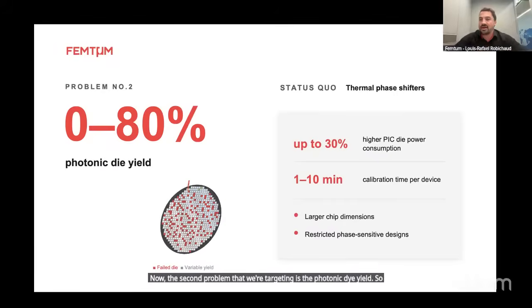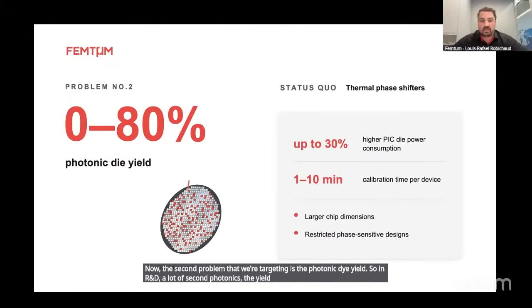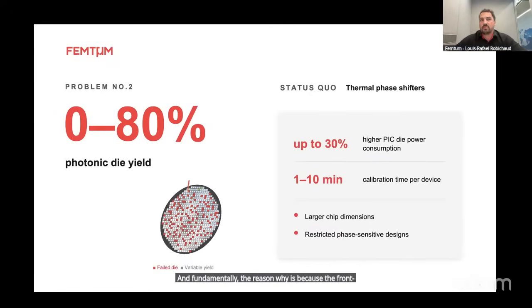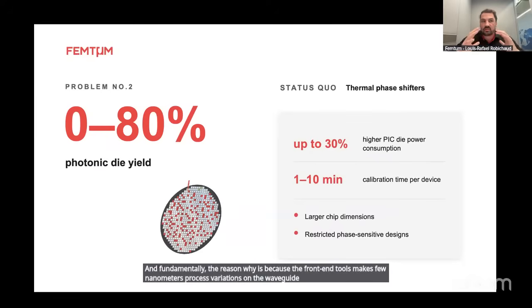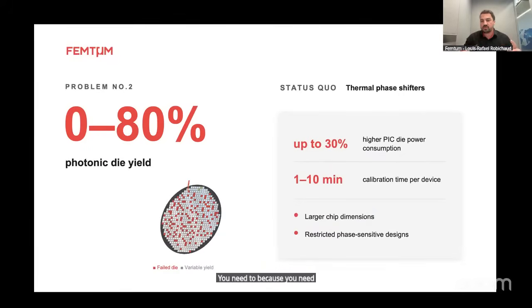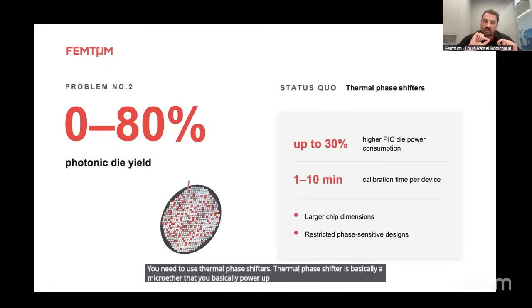In R&D silicon photonics, the yield is like 0%, or 5%, 10%. And in production nowadays, it's between 50 and 80%. Fundamentally, the reason is that the front-end tools make few-nanometer process variations on the waveguide. So the width, the height, the angles, and the surface roughness are not as precise as they should be. So nowadays, to make silicon photonics work, you need to use thermal phase shifters. A thermal phase shifter is basically a micro heater that you power up 24/7, and you need to calibrate it to synchronize the optical response of each waveguide inside those phase-sensitive structures.